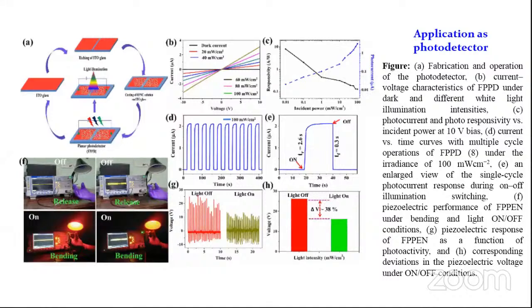Then we have checked the photo current and responsivity with incident power. Figure D represents the reproducibility of the PNG under 10 volt application. And figure E represents the enlarged view of a single peak. As you can see here, the rise time and fall time are very small, so it will quickly detect the UV light.